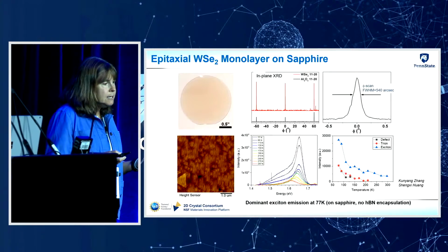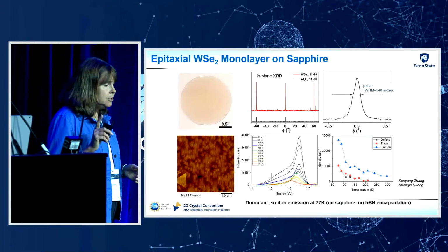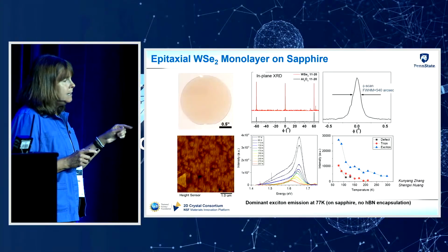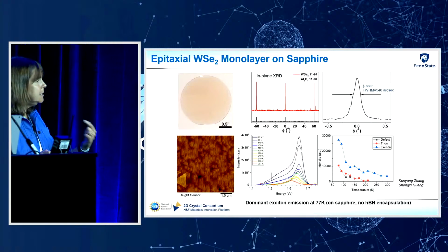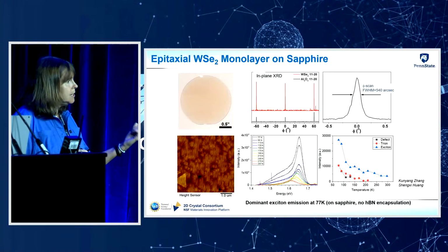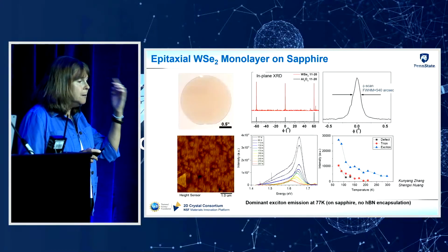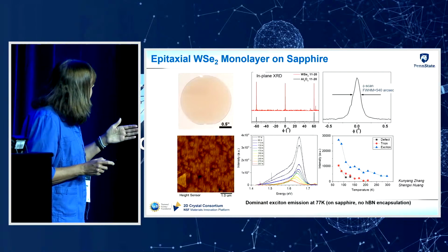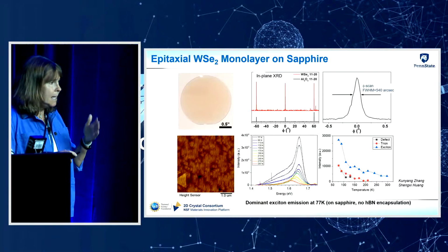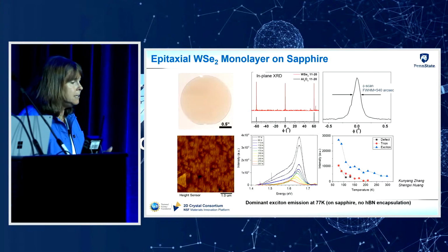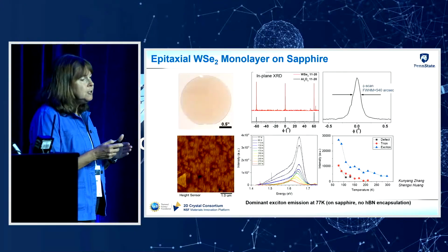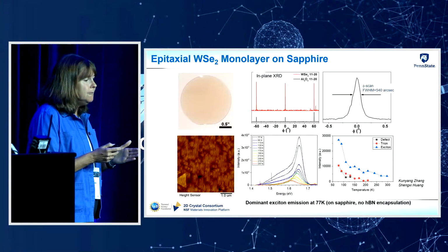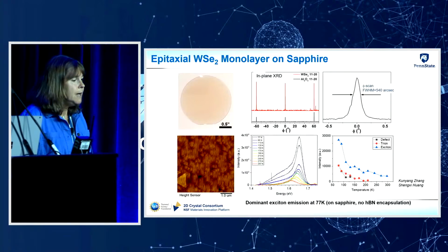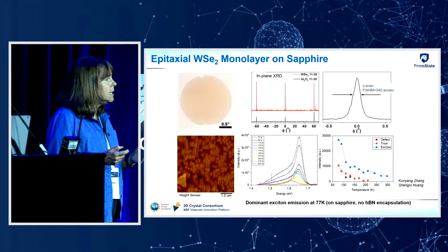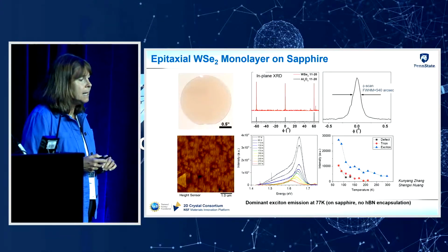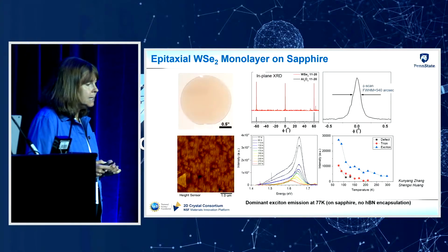If we do in-plane X-ray diffraction, which is shown in the top figures, this is an in-plane phi scan. So it measures the symmetry of the substrate peaks and also the film peaks. And we can see that the tungsten diselenide is growing epitaxially on the sapphire as we expected. If we measure the full width at half maximum of one of our phi scan peaks, we get a value around 540 arc seconds, which is pretty good for a heteroepitaxial film that's only 3 atoms thick.